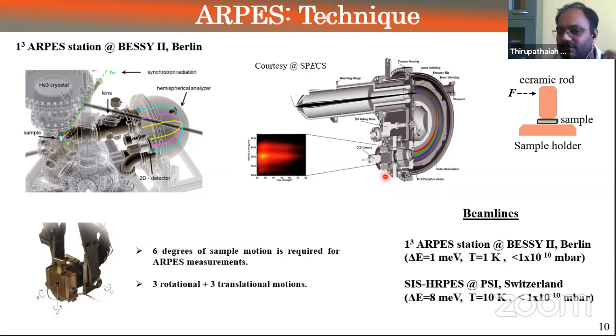Since this is a surface sensitive technique, we always have to have a very clean surface. Since we work mostly on single crystals, this is the technique that we always use. This is the sample holder, and this is a small ceramic rod. In between, we attach a sample using silver paste or any highly conductive glue. Then this whole setup goes into the ultra high vacuum chamber, and we gently knock on top so that we cleave the sample, ending up with a very clean surface.